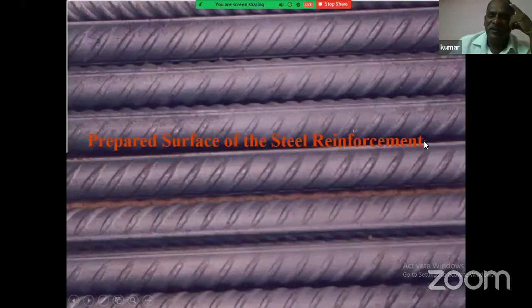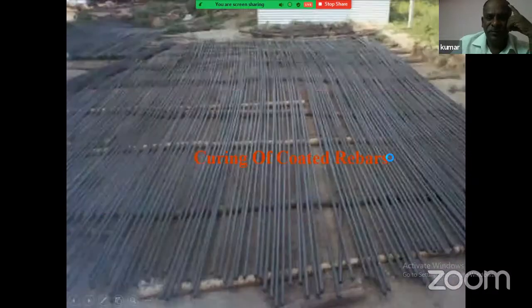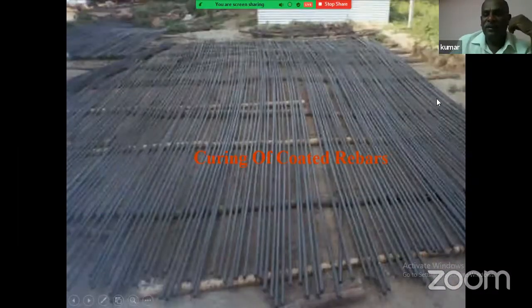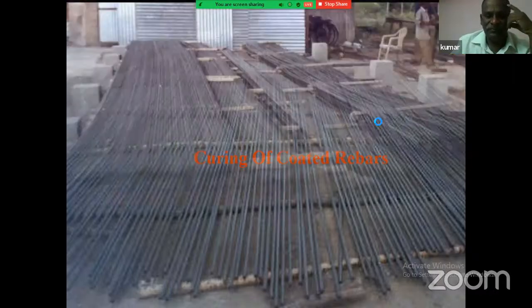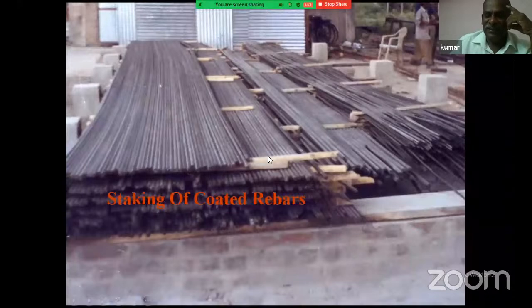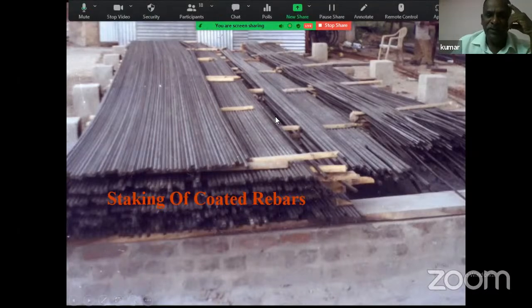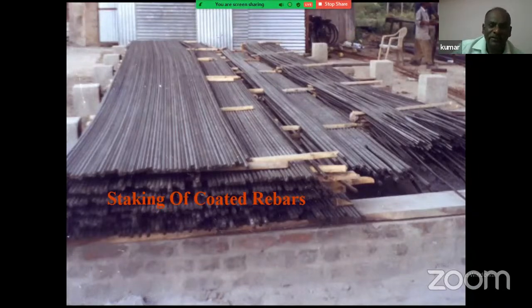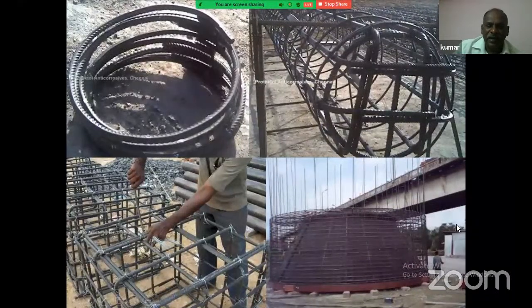This is the surface prepared reinforcement. You are seeing the completed reinforcement which is kept for curing. So now it can be stacked like this. We have to have a wooden plank for each layer and stack. These are the coated steel reinforcement. It is actually one of the railway bridges where the photographs were taken. You see that after the stacking, it can be bent. So it is not damaging. It is not at all damaging.